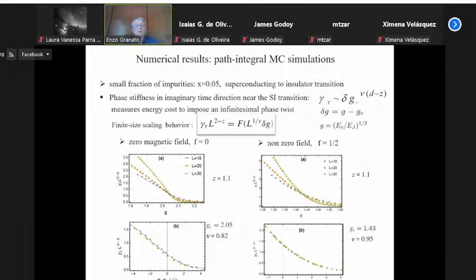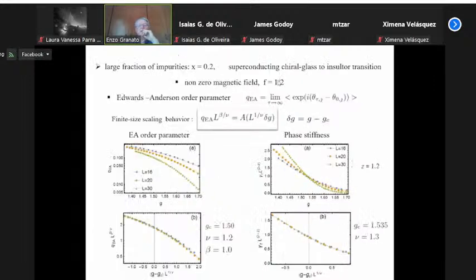And here is just an illustration of one of these calculations for a small fractional disorder, a small fractional impurity concentration. With a small fractional impurity, you still expect a superconductor-insulator transition. Here we look at the phase stiffness behavior, and as we show here on the left, there is a phase transition which can be identified by the crossing of the phase stiffness for different system sizes, from which you can get the critical exponent. You get a critical exponent here for zero field and for f equal to 1/2 that are different from each other. So they are in different universality classes. So at small disorder, there is still a superconductor-insulator transition, and the f equal to 0 and f equal to 1/2 are in different universality classes. Now, if the disorder is very large, the system is in a glass phase, the chiral glass phase.